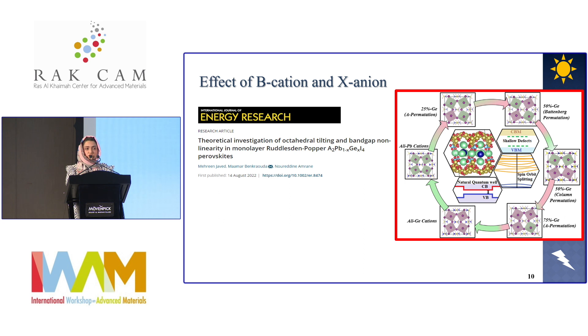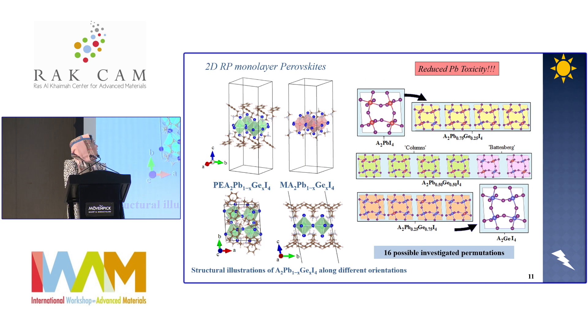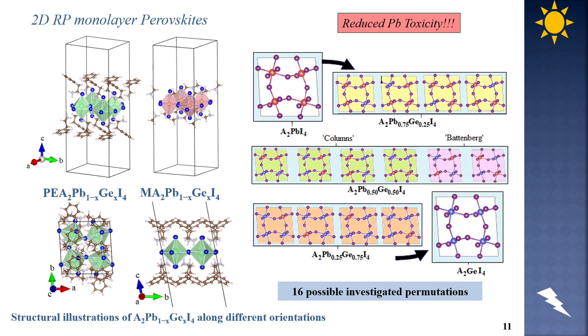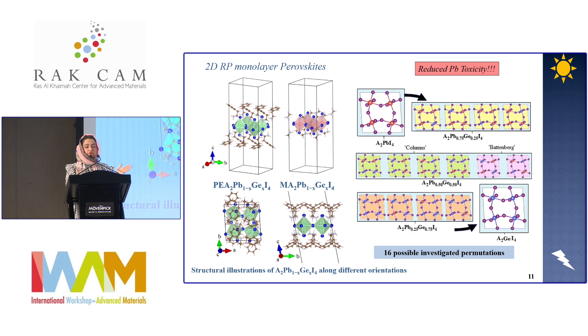I have studied 16 structures depending on different concentrations of lead. In my structure, the green and pink represent the inorganic layer, while on the top and bottom are organic layers called spacer cations — these are hydrophobic, water-repellent, or moisture-resistant, providing stability against water molecules. I have studied 16 permutations where lead is replaced with germanium at four concentrations: 25%, 50%, 75%, and 100%. For 50%, there are six permutations based on the location of the dopant within the crystal structure — all possibilities have been studied.